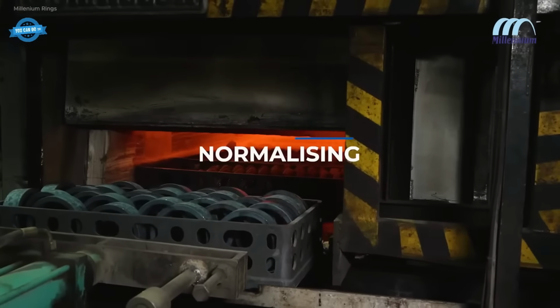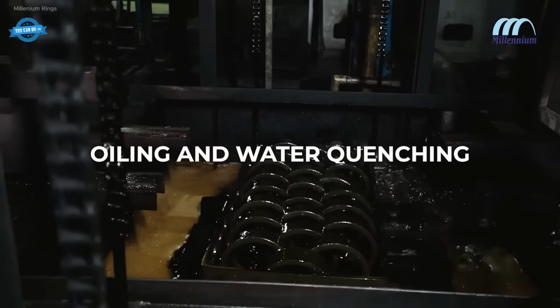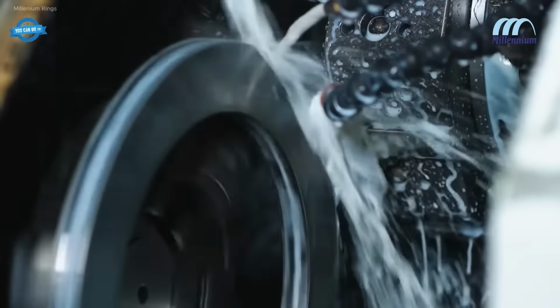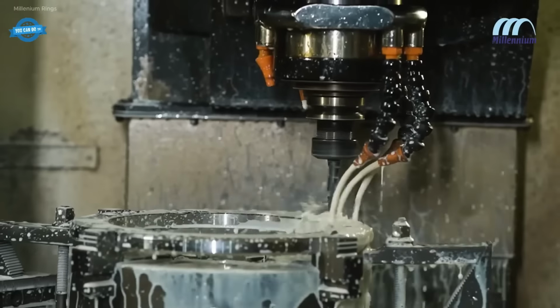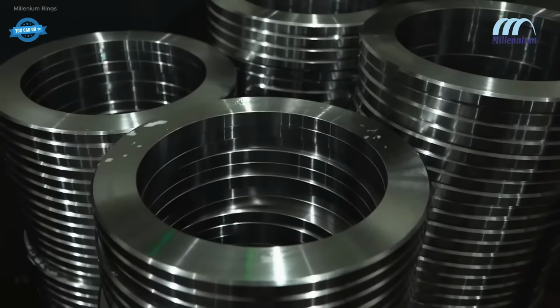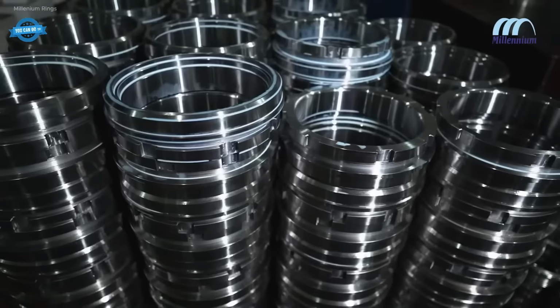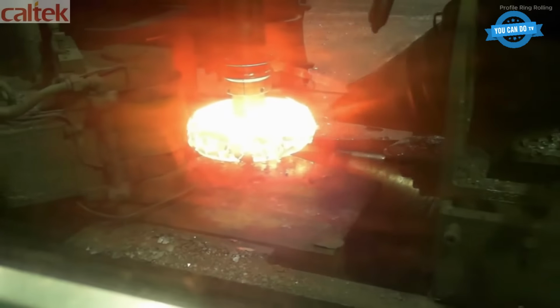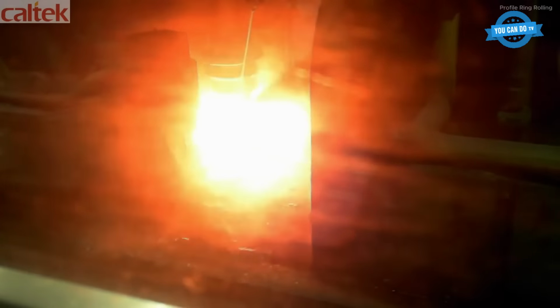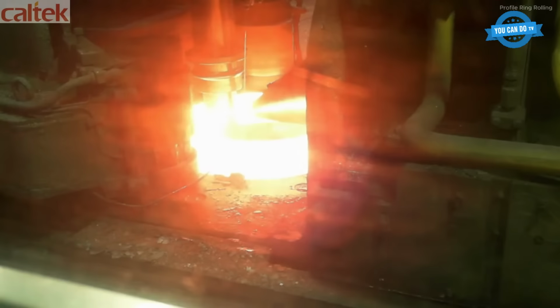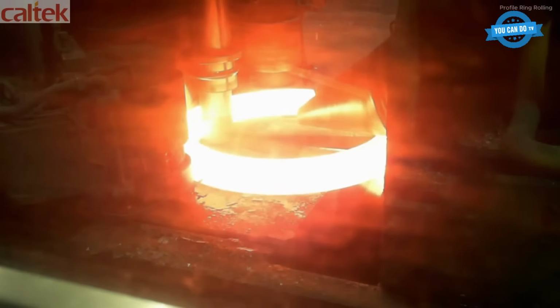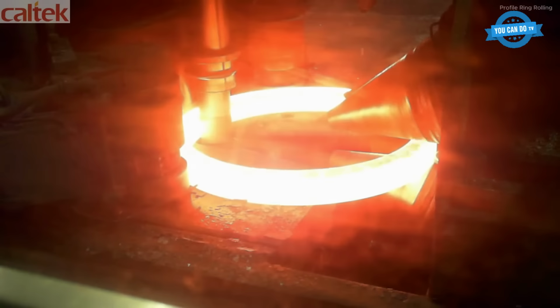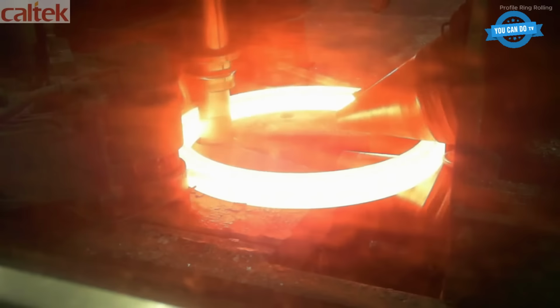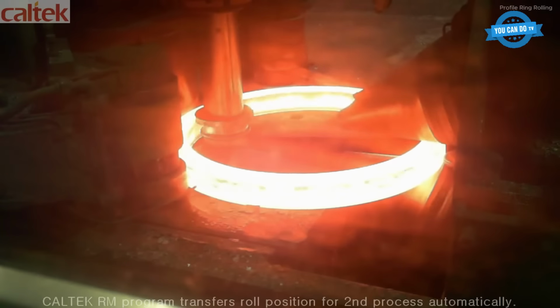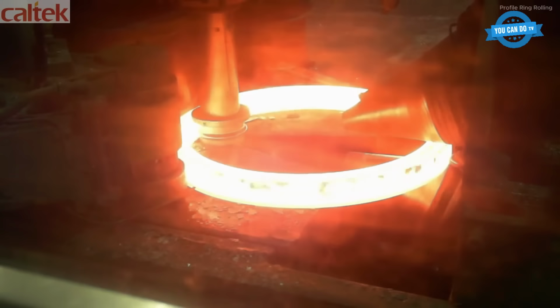CNC/VMC machining centers finish to tight tolerances, while spectrometers, ultrasonic inspection, and hardness testers validate chemistry, soundness, and mechanical properties. Dual ring rolling enables simultaneous forming of 2 rings, increasing efficiency and consistency in profile ring production. Using precision-controlled hydraulic presses and CNC-guided rollers, the process ensures uniform wall thickness and shape. It's ideal for symmetrical profile rings in aerospace, bearings, and flange industries, reducing cycle time significantly.